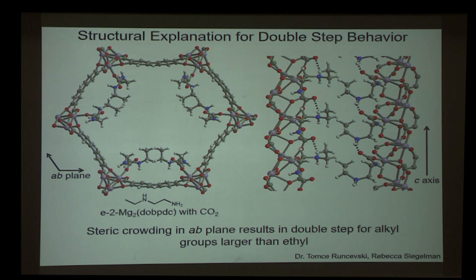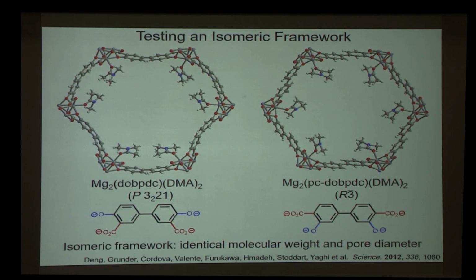What I hypothesized is that when we went to anything larger than ethyl, we were creating steric interference between sites. And this steric interference was preventing the full capture of CO2 at every site in the material. And if this hypothesis is correct, what I needed to do is alleviate steric crowding at this key position. The approach I took to address this problem was to use an isomeric framework.